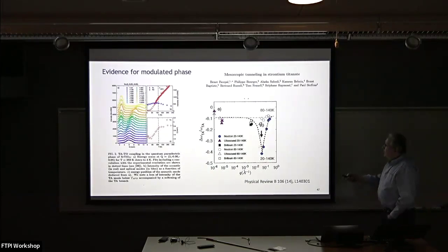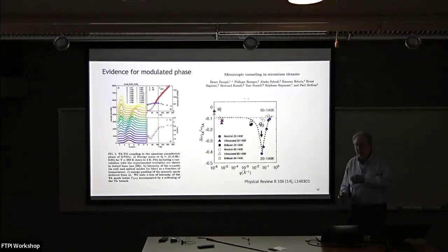Notice, of course, that this is still a solid. So if you measure the sound velocity at much longer wavelengths, which you can do, it really is not softening at all. It's just something that's happening, and also at larger wavelengths too. So these are waves with a very long period. I don't have any evidence in this data, however, that any symmetry got broken, that there's an underlying phase which has all of those fluctuations.